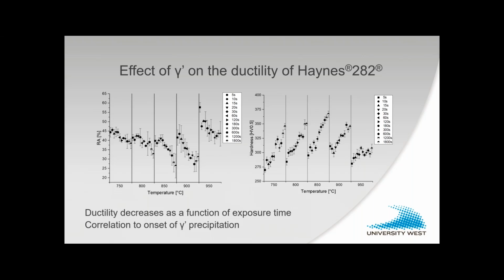So ductility decrease as a function of exposure time, and that correlates to the onset of the gamma prime precipitation. So we couple this type of testing with the sophisticated characterization using transmission electron microscope as well as scanning electron microscope. And we did it not only for 282, but also for Waspaloy and some other materials, and it's all published in different journals.